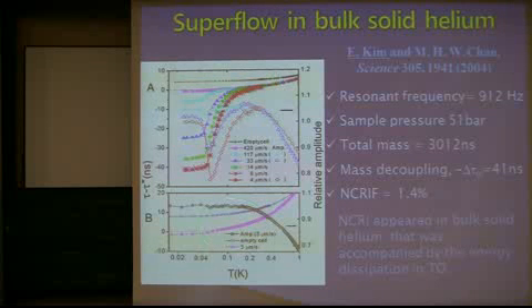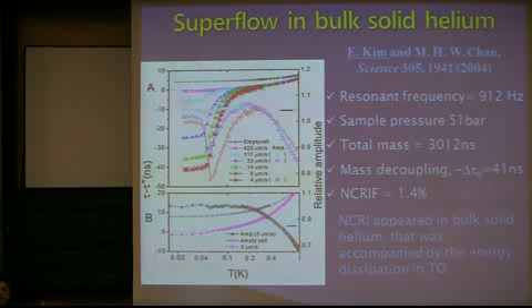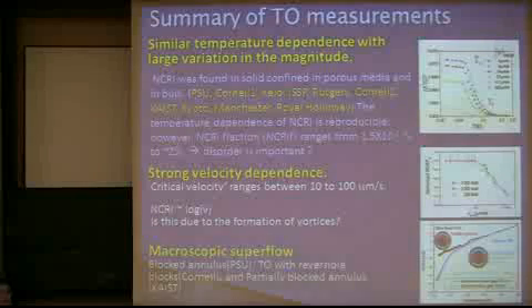And in the lower panel, if you block the annular flow channel, then the total signal is strongly suppressed. It's just gone, because this is not a local phenomenon. If it were a local phenomenon, the effect must still be there. So this is the second experiment.